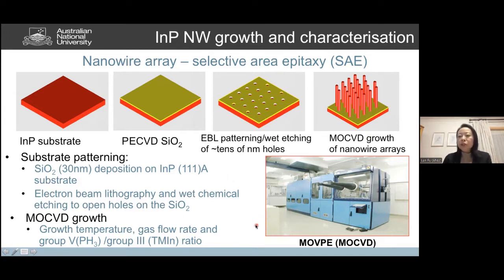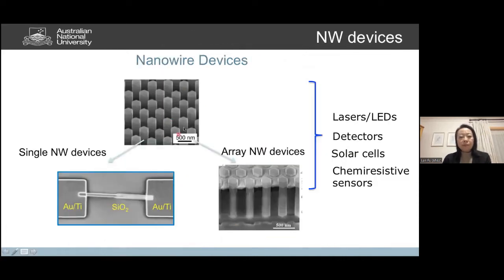Obviously we have to do a lot of optimization of the MOCVD growth in terms of the gas flow rate, the group V/III ratios, as well as the growth temperatures to achieve good nanowire growth. So this is an SEM image of a typical indium phosphide nanowire array grown in our group. Based on this kind of nanowire structure, we can fabricate two types of nanowire devices. One is a single nanowire device, where we normally knock these little nanowires down and transfer them onto another substrate, in this case silicon dioxide on silicon. Then we use electron beam lithography to fabricate contacts on top of the nanowires. So this is a single nanowire LED fabricated in our group, where we have to do some standard device fabrication to make a single nanowire device.